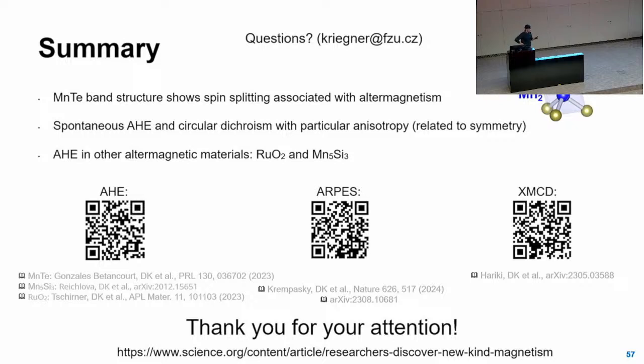But it's the first and only material where we have this kind of agreement between the calculation and the experiment. For the others, the problem is often also that the measurement quality is much lower, and then you can dream of the agreement, but I can also not say it disagrees, right, because you don't see enough features. I guess you know what I'm speaking about. But generally, I think it's a very useful tool for us, absolutely essential actually. But of course, one has to always treat it with a grain of salt and know how to look at it.